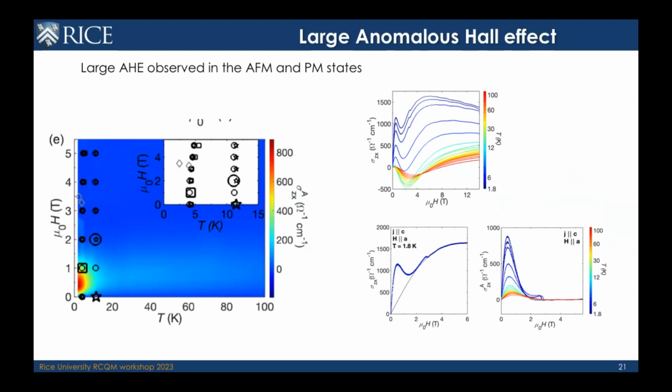What makes you confident that you have the right to take that curve as your background, saying that's the 2-band? You could go 3-band, 4-band, 5-band. Is there any particular reason you think your 2-band model is capturing the band structure? No, I'm just saying that at high fields, we fit it with this 2-band model. That's the best we can do. I'm not saying that this is the absolute description of what the conductivity is, but I don't know how I would capture this peak over here with any number of bands.